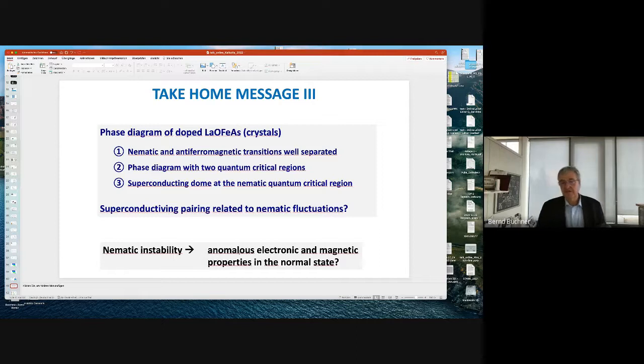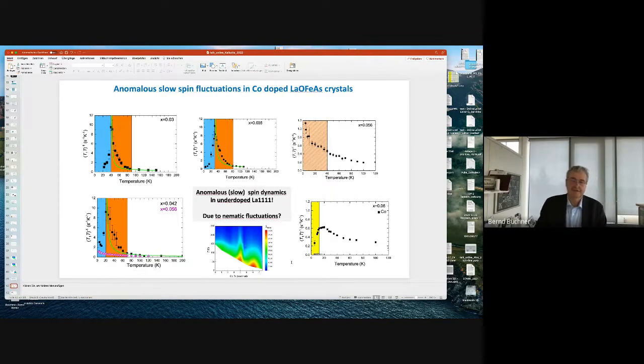And it's also clear if we have these nematic fluctuations, there will be anomalous electronic and magnetic properties in the normal state connected to these nematic fluctuations. And one example is NMR. And maybe it's a little bit difficult, but I'll try my best. So these are measurements now of the relaxation rate as a function of temperature for different crystals, different dopings. So these are the typical magnets. If you have the magnets, you have this divergence.